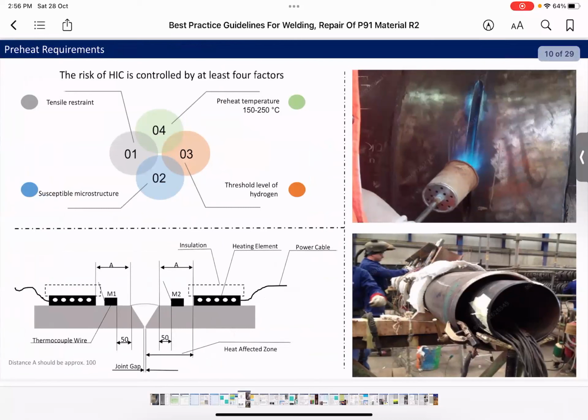So preheat requirements. The risk here is the hydrogen-induced cracking. So this hydrogen-induced cracking can be controlled by these factors: the stresses in the joint or the tensile restraints, the susceptible microstructure. We know that P91 has a microstructure that can be susceptible to hydrogen-induced cracking if improperly controlled. And these things, these 1 and 2, cannot be controlled by welding. What we can control by welding is the hydrogen diffusion in the thickness or in the steel.